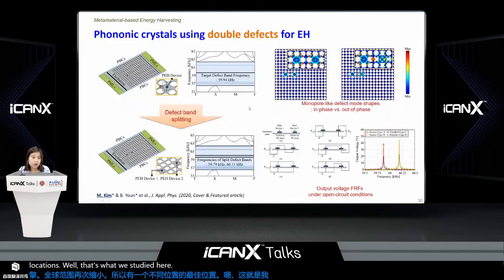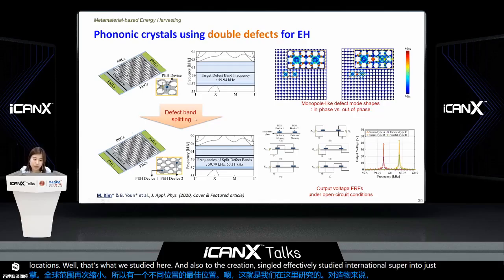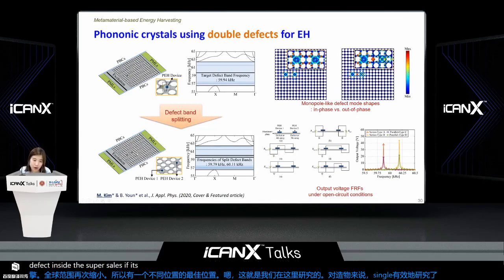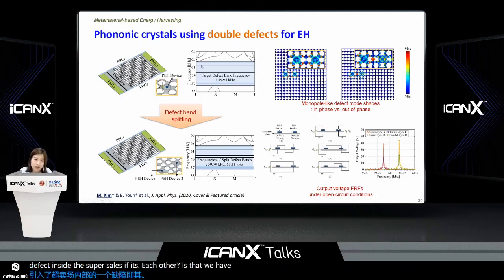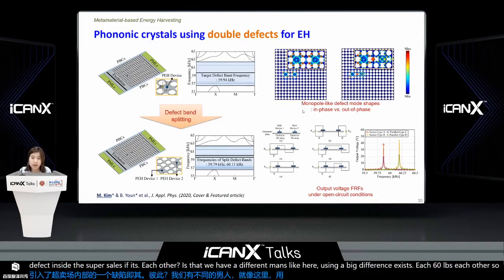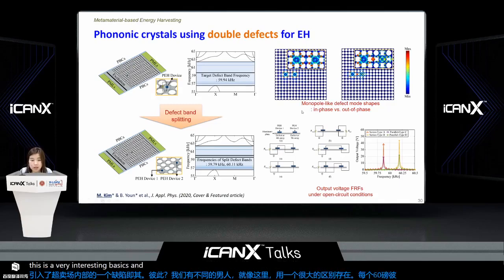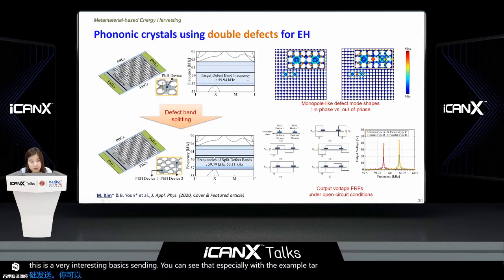And also, we are not limited to the creation of a single defect. We studied the interaction of double defects inside the supercells. Once we introduce two defects inside the supercells, if they are not too far from each other, they interact with each other. The result is that where a single defect gives six defect bands, these six defect bands are split, so in total 12. This is very interesting physics, especially with the example of the target defect band frequency about here, which is split into two like here.